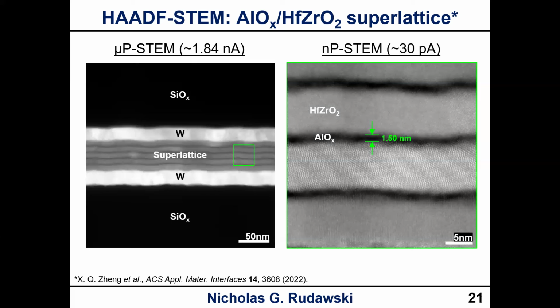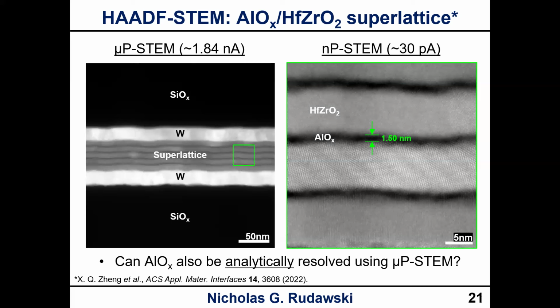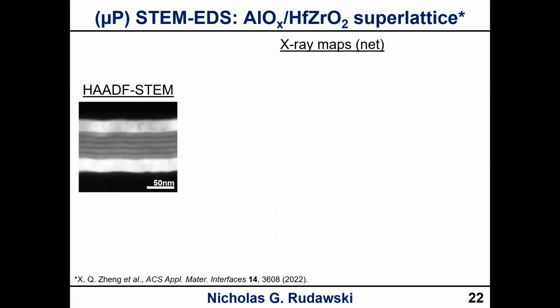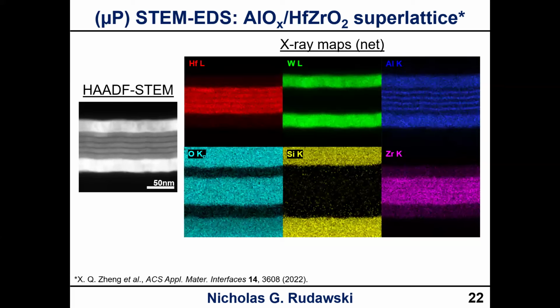Okay, so the question is, right, we can see that in the microprobe STEM image as well as the nanoprobe STEM image. Okay, but can we also see that analytically if we do, say, EDS mapping? Okay, so again, if we do EDS mapping, there's our HAADF STEM image and there's our X-ray maps for the 6 relevant elements. Okay, and so we can see very clearly that yes, we can resolve the alumina very clearly.